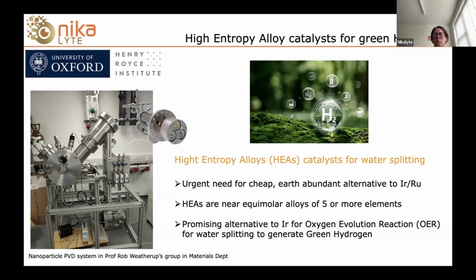And these constitute from a wide choice of materials, including nickel, iron, cobalt, molybdenum, aluminium, chromium. And these are all very cheap and earth abundant, so extremely attractive compared to the iridium and ruthenium, the platinum group elements. So the particular reaction that Rob's group were looking at is the oxygen evolution reaction. So we're comparing the performance of these alloys to iridium in the water splitting reaction to generate green hydrogen.